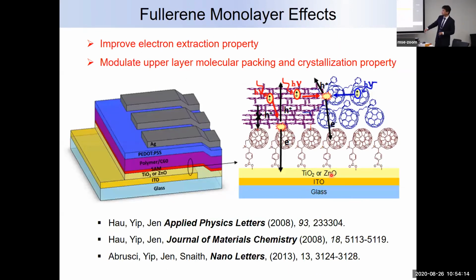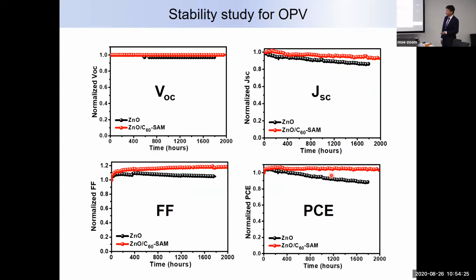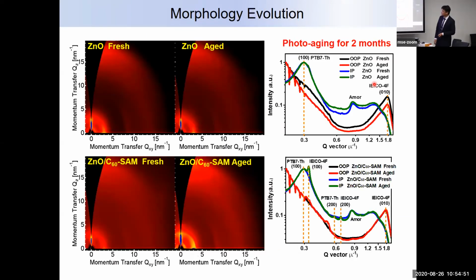And of course, this SAM strategy is not new, but it is new to evaluate the stability. We used this strategy to improve performance 10 years ago when I was still in Alex's group, okay? And of course, we are trying to understand why. We see that with this SAM modification, the fill factor continues to increase during illumination, and then eventually they plateau. Current density is decreasing a little bit, so eventually they balance the effect for the power conversion efficiency. But for the unmodified one, both fill factor and Jsc are decreasing. And of course, we know that it probably is due to the morphological effect.